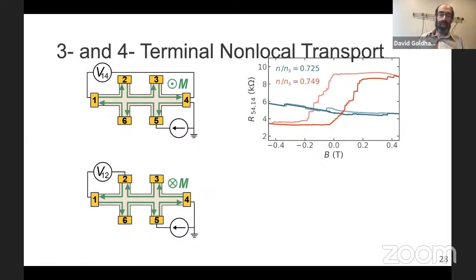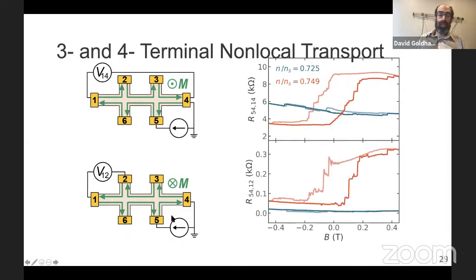And 4-terminal resistance, ideally in this non-local configuration, should have a 0 resistance. You drive a current on one side, measure a voltage far away from there. There should be almost 0 signal. And we see a signal, and it turns out that's because of a combination of non-local edge transport and also some diffusive transport in the system.